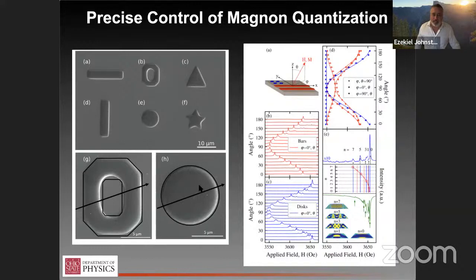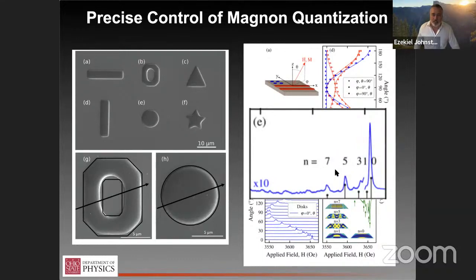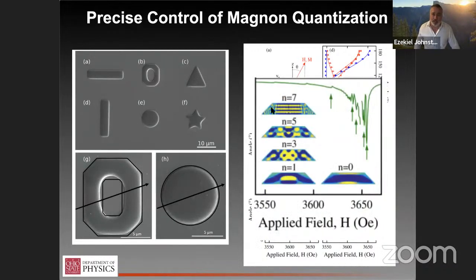But if we look at the damping in these disks, we get exactly the same value of 4 × 10⁻⁵ that we do for thin films. So this is itself pretty unprecedented for magnetic systems. Patterning magnetic systems almost always leaves edge states that contribute to damping or dephasing in the dynamics. And using this patterning and growth technique for YIG, we completely sidestep that. The other thing I want to point out, and I know there's a lot of data here, this is characterizing both bars and disks, but in this bottom right corner, the blue is experiment and the next two panels are theory. You can see here, we see harmonics of the fundamental mode up to 7 that we can identify both analytically and numerically. So this green is a numerical simulation where the arrows are representing the harmonics that we see in experiment.